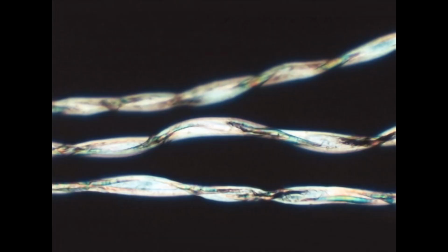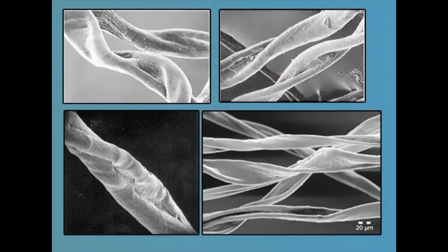This fiber, which is 2.5 inches in size, when you see it under a microscope, looks like a flat ribbon, and it has a natural twist, which we call convolutions. These natural twists are formed when the fiber is exposed to the outside climate, the cell sap which is present gets dried up, and then it forms a flat ribbon, and flat ribbons become easily twisted. That is the natural twist present in these cotton fibers. And the diameter of the cotton may range from 12 to 20 microns.